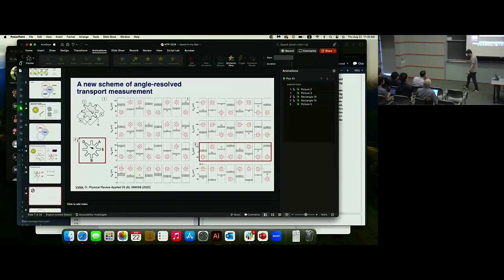Right, so at the beginning, instead of just the longitudinal and transverse response, we do a very extensive measurement, like 50, 100 configurations. If all of them can fit to the same conductivity matrix for linear, or conductivity tensor for nonlinear, then we know that the sample is uniform. That's the criterion: even as the superconductivity is onsetting, we can still do a pretty good angular fit. So it must be onsetting in a way that, for the transport measurement, it's uniform. Maybe microscopically it has non-uniformity that's beyond our control.